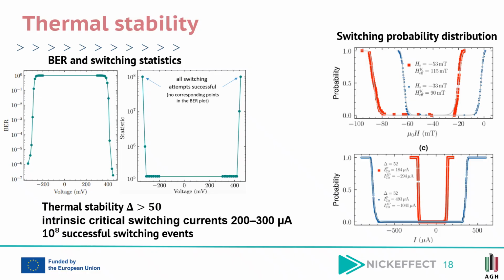The graphs on the left present the measured BER, or bit error rate, characteristics, together with switching statistics as a function of applied voltage. The experiment starts at low voltage amplitude and continues to the high end. BER equal to 1 means all switching attempts were unsuccessful. BER equal to 0 means all switching attempts were successful. For the outermost points in the right graph, 10 to the power of 8, there is no corresponding point in the BER plot. At those voltages, all switching attempts were successful.